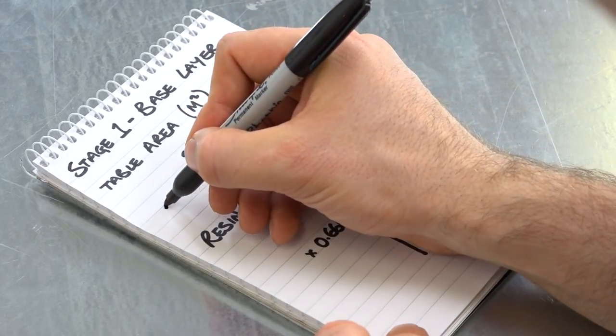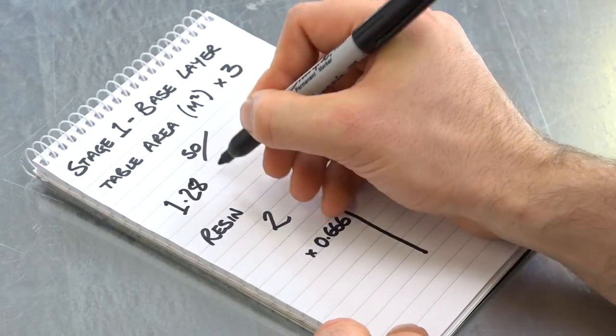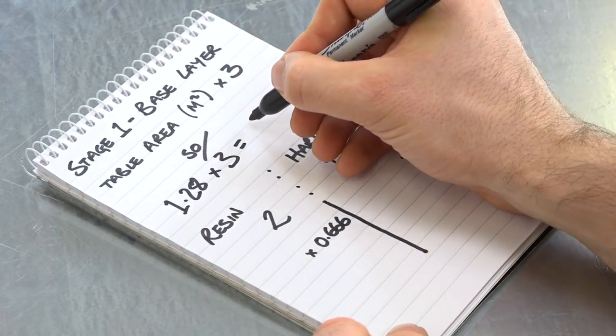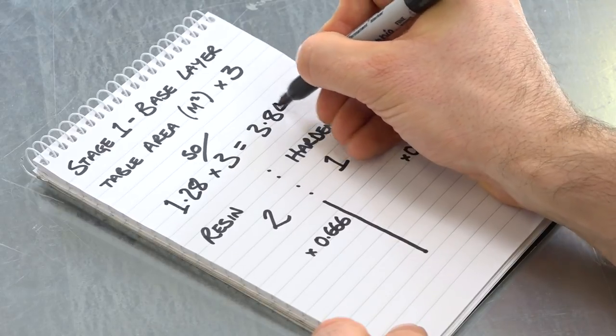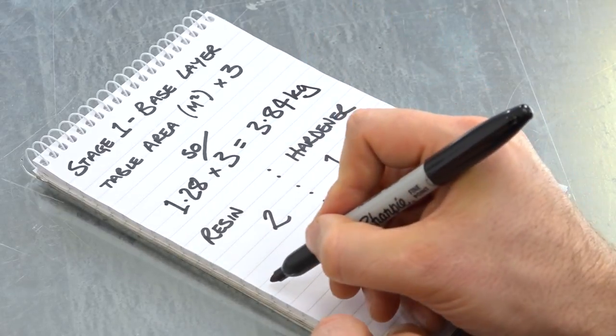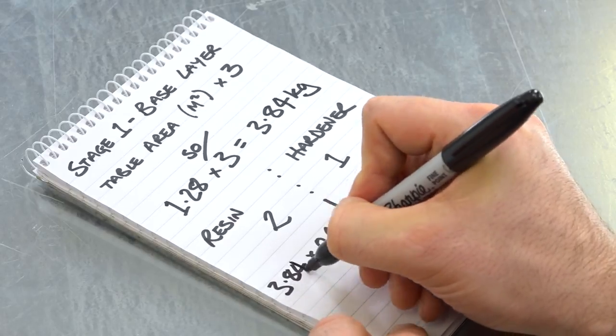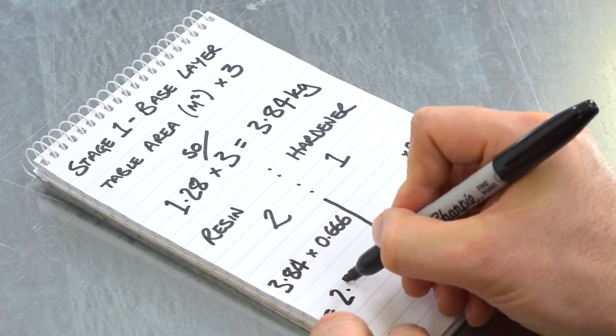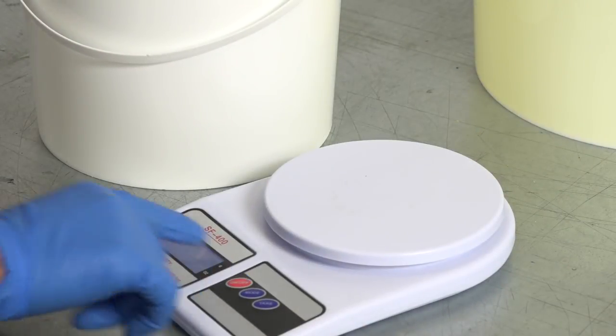So, this is stage one. This is where we pour the 3mm base layer. Firstly, we need to work out exactly how much resin we need to do this stage. And the simple calculation is to take the area of the table in square meters and multiply that by 3. This table is 0.8 meters by 1.6 meters, which is 1.28 square meters. 1.28 multiplied by 3 is 3.84, so I'll need 3.84 kilograms of resin. GlassCast 3 uses a 2-to-1 mix ratio by weight. This means I'll need 2.56 kilograms of resin and 1.28 kilograms of hardener.